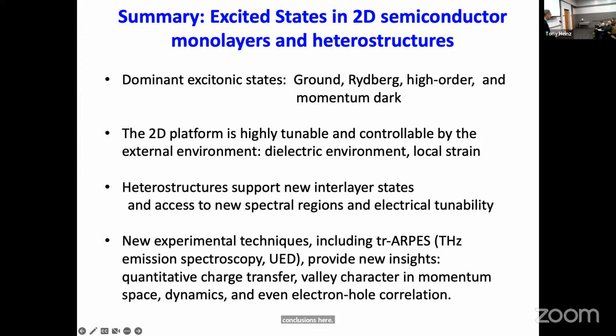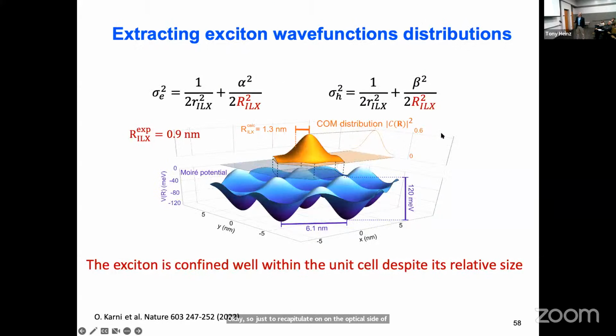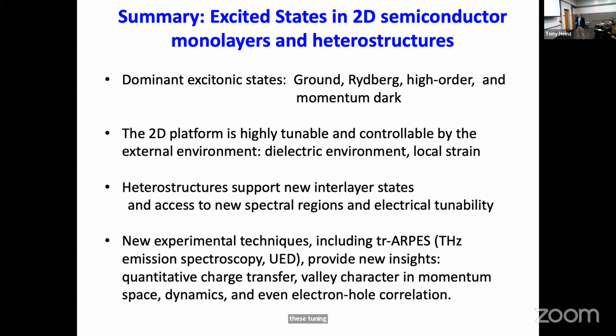Okay, so just to recapitulate, on the optical side of these 2D materials, hope you'll carry away the idea, because of the reduced dimensionality and mostly because of the very reduced dielectric screening, all the optical excitations are dominated by correlated electron hole pair states, the excitons, and you see the ground state Rydberg states. You see these higher order correlated states like biexcitons, and with the time resolved photoemission, we can also see momentum dark states. The 2D platform is very tunable in ways that often don't apply to bulk materials.